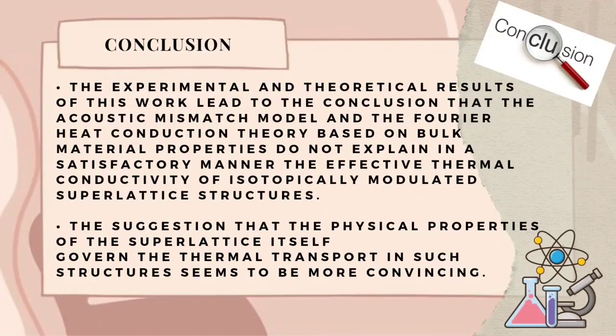Next, conclusion. The experimental and theoretical results of this work lead to the conclusion that the acoustic mismatch model and the Fourier heat conduction theory based on bulk material properties do not explain in a satisfactory manner the effective thermal conductivity of isotopically modulated superlattice structures. The suggestion that the physical properties of the superlattice itself govern the thermal transport in such structures seems to be more convincing. That's all from me.